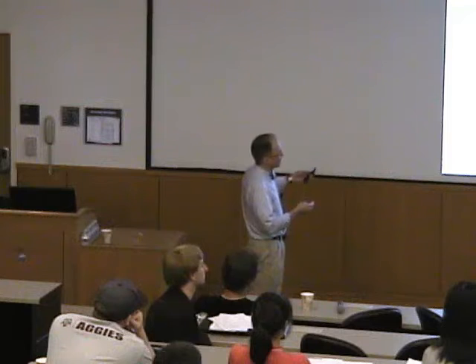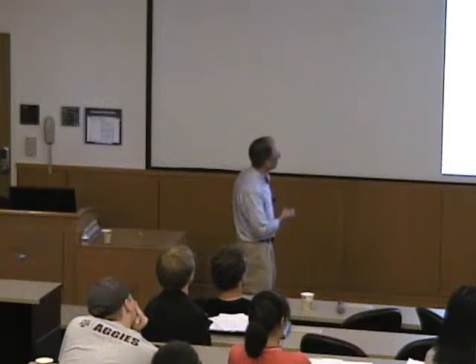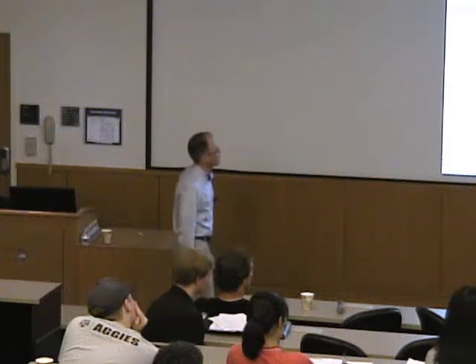And the idea in the case of these experiments is that one can find, as one increases the rate of a cyclic voltammetry experiment, and that's what's shown here, there is a peak separation that is engendered. And that peak separation reflects the rate at which we can have electron transfer occurring into the ferrocene and back out. Or one can examine a transient mode as, again, a sort of potential step mode where the magnitude of the step was varied in the case of the Science paper and the unimolecular rate determined directly from the kinetic traces of current. So again, this is a current-based readout.